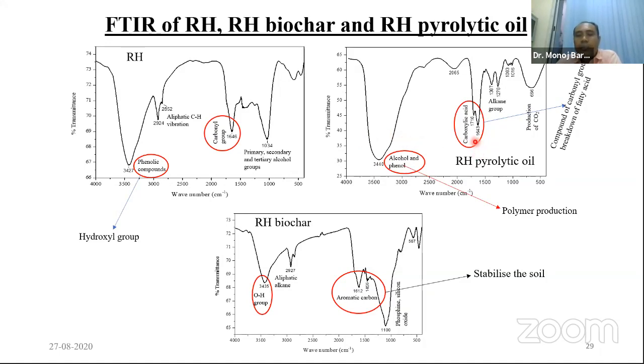Similarly, the peaks obtained at around 1600 wave number indicate the presence of carboxylic acid in the bio-oil or bio liquid, because this is a liquid product. And we know that this carboxylic acid is basically under a carbonyl group, and this is obtained by the breakdown of the fatty acid, which is a very common and useful element of the bio-oil.